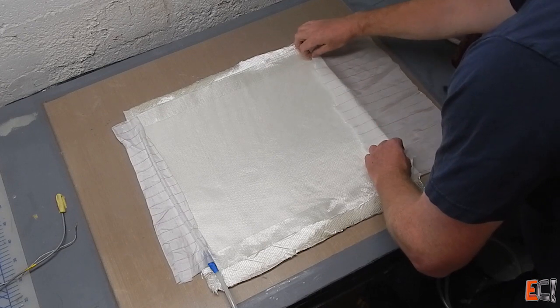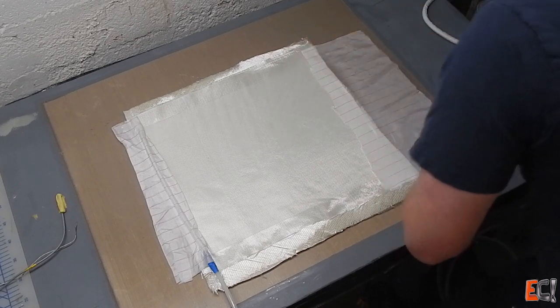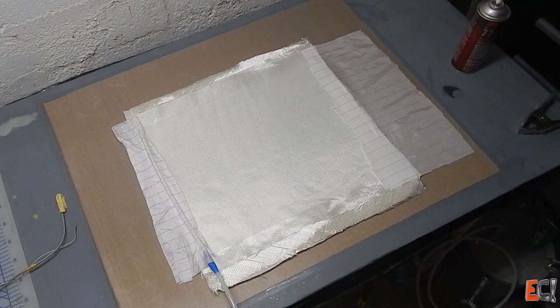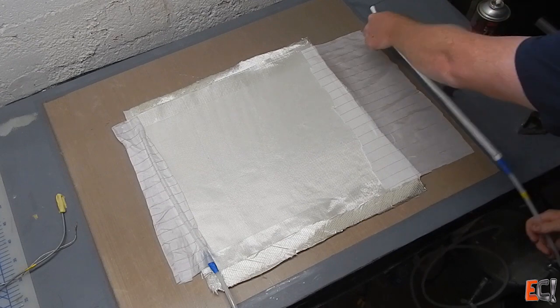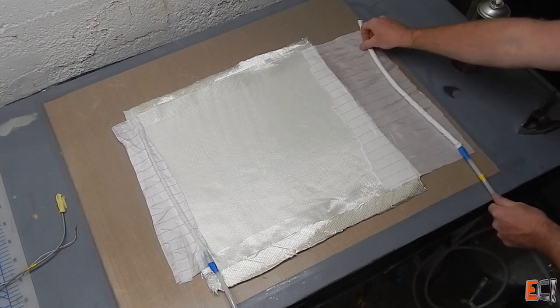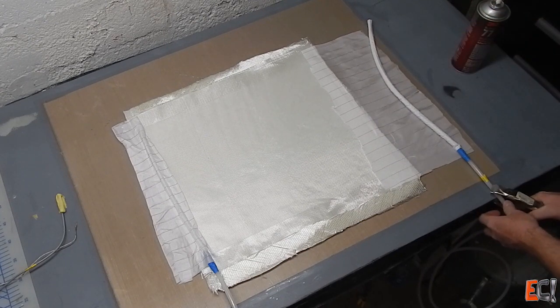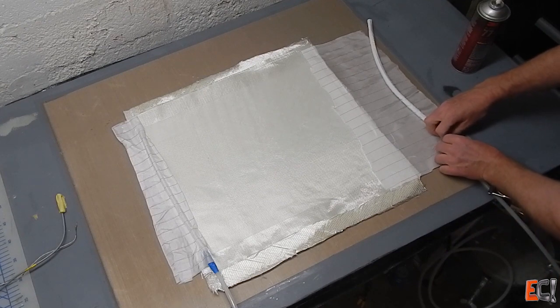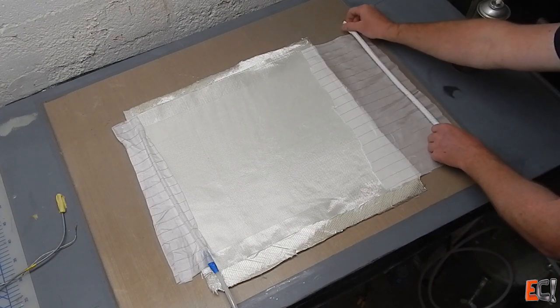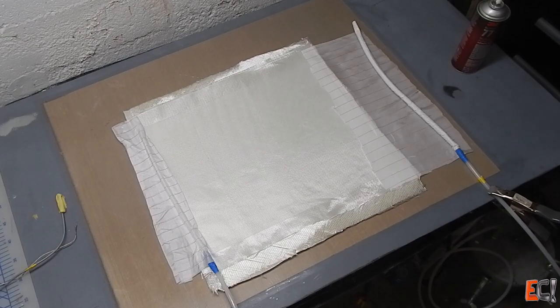There'll still be quite a bit of friction, so I'm really racing the friction of the resin flowing through the fibers against the lower resin viscosity against the gel time of the resin. And on the outside, the outlet side for vacuum, here's a piece of MTI hose and a nice long peel ply vacuum break, but the resin probably won't get that far.